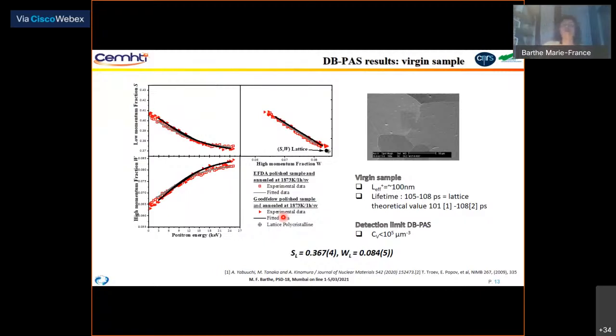First, the virgin sample, that means the sample before irradiation. You can see here some Doppler broadening measurements as a function of positron energy. And you can see that this data can be fitted with an effective diffusion length for positrons of about 100 nanometers. We measured the lifetime in this virgin sample and obtained about 105 picoseconds, which corresponds to the theoretical value for the annihilation of positrons in the lattice. And we obtain the annihilation characteristics, that means S and W in the lattice, which are here.